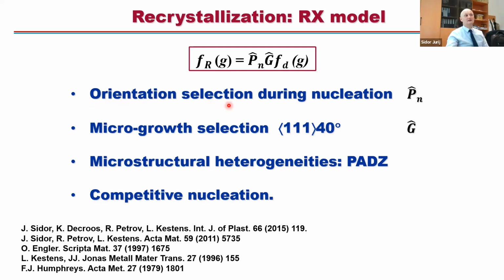And then we apply so-called orientation selection or nucleation operator, which implies that you employ low stored energy nucleation. So only those nuclei with the lowest possible energy will grow. In fact, physically, it's sound because the system tries to reduce its stored energy, and only those nuclei will grow which have lowest possible energy. So the results of this work were published in a couple of journals, in IJP, Acta